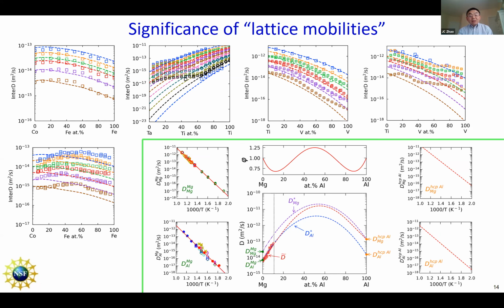So let's see how important that is, to have the foundation of the self-diffusion and the impurity. Again, you can see this set of data bended over, and the impurity diffusion is much, much smaller. There's a very clear explanation why this kind of phenomenon takes place. Also we need the metastable states so that we can do a much better job in fitting this one. So it's extremely important, just like the lattice stability for thermodynamics. The lattice mobility is also equally important.